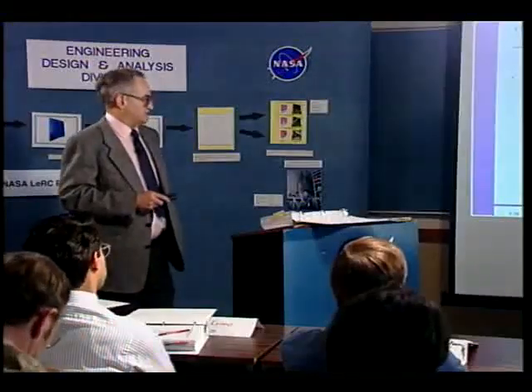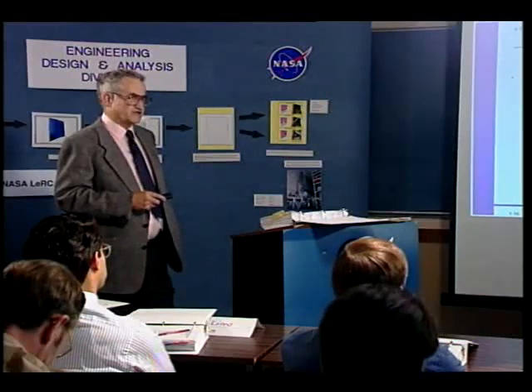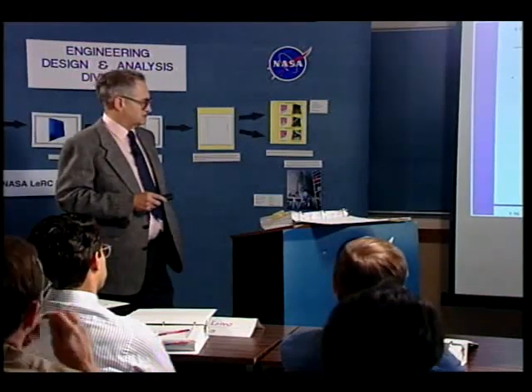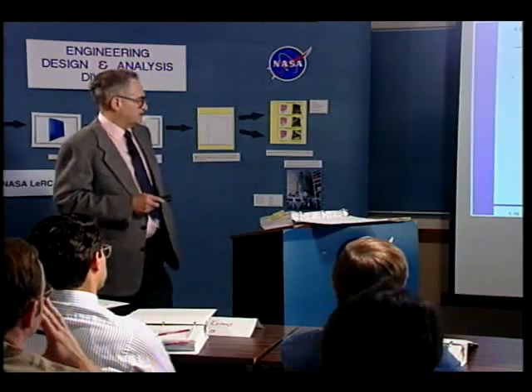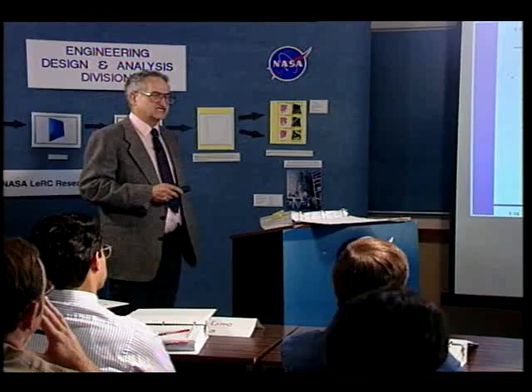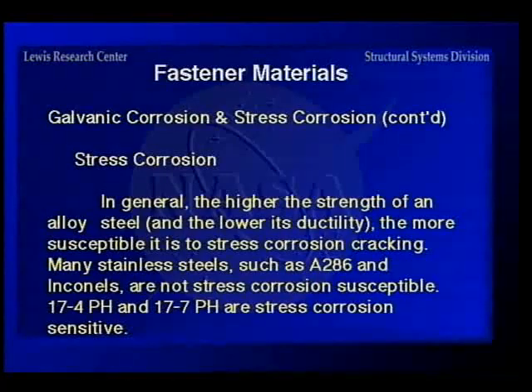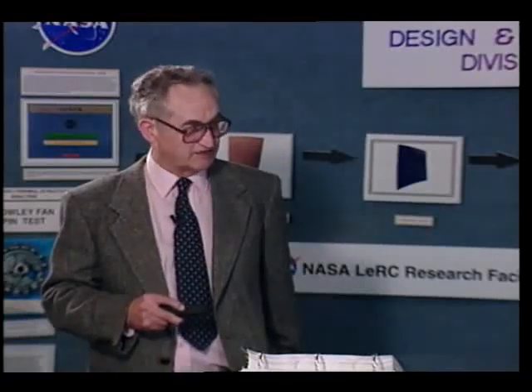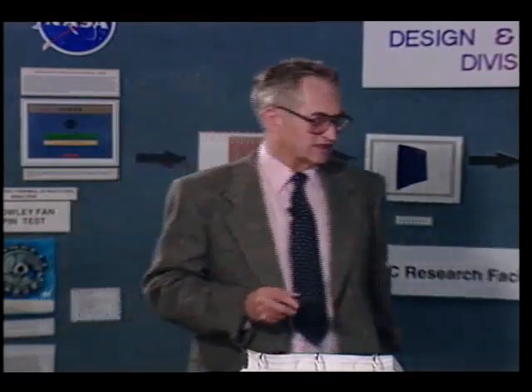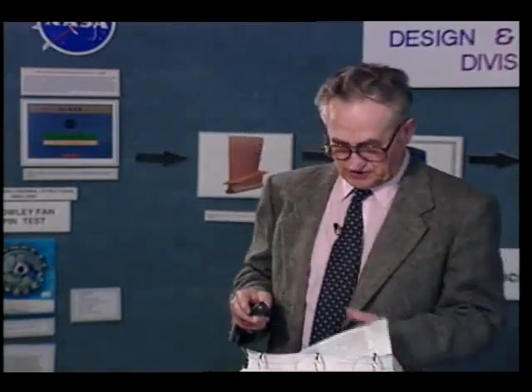Now, one of the reasons why I don't propose using the super high-strength alloy steel fasteners, if you can avoid it, is that the higher the strength, the more sensitive it is to stress corrosion. So you try to steer clear of using super high-strength fasteners in alloy steel for that reason. The stainless steels, most of them are not stress corrosion susceptible, other than the precipitation hardening 17-4 and 17-7. So you ought to look at that before you select the fasteners that you're going to use.